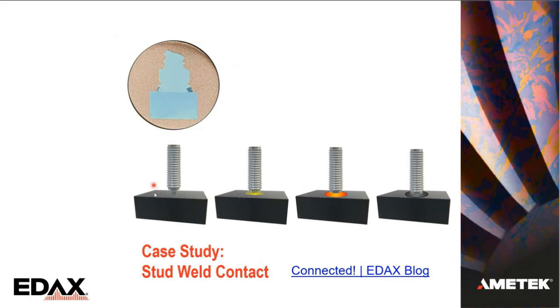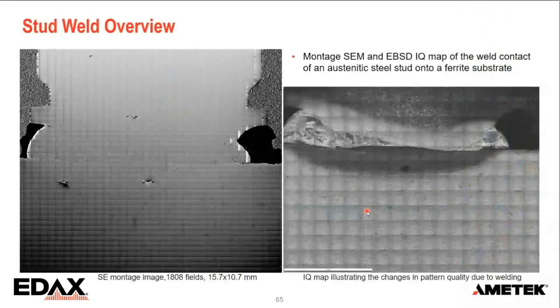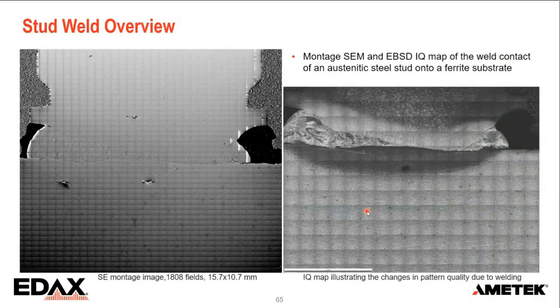And stud welding is a tool or a technique to connect a rod, a threaded rod, like from a bolt, for example, onto a substrate, put them together, get electrical arcing happening that heats up the interface. Then you get a melt pool here at the bottom, and then you just plunge the stud into this melt pool, let it cool down in a few milliseconds, and you have a very strong weld contact. That's the method for stud welding. It's very fast. It's milliseconds that all of this happens. And with EBSD, we can look in a lot of detail what is happening there.